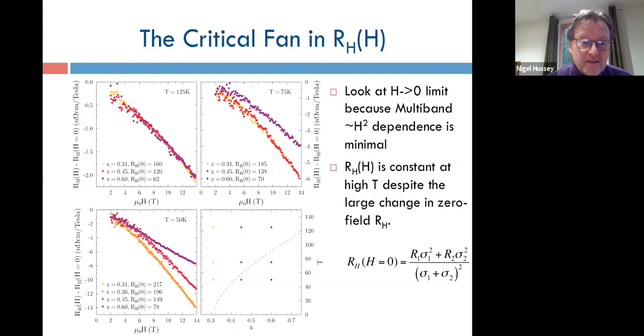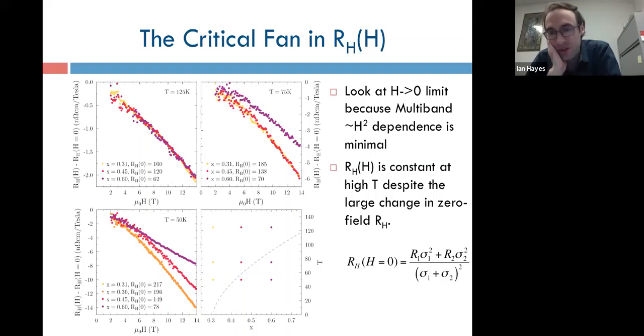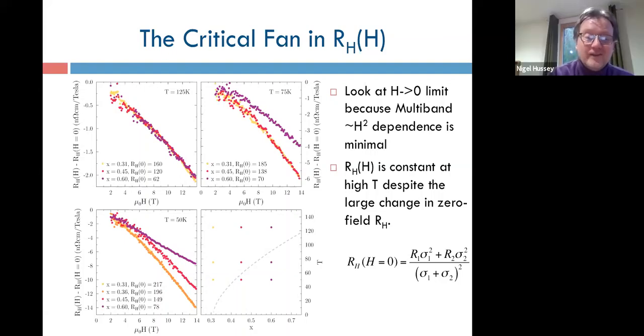Your data suggests a very systematic behavior, almost independent of the model. We've been measuring magnetoresistance and Hall effect, and we really struggle to fit the two side by side in any kind of Boltzmann type picture. I guess it's probably the same here too. Yeah, next to each other is fairly hard. It may well be that a lot of the magnetoresistance is coming from the shape of the Fermi surface, and then there's some extra ingredient that shows up in the Hall coefficient that is separate from the Fermi surface. It sits on top of it. Interesting. It's unclear how they're related. Thank you.